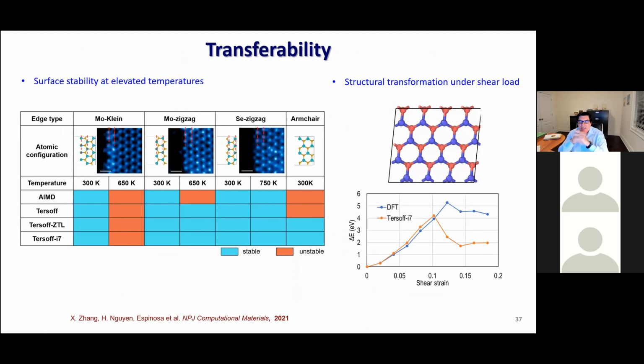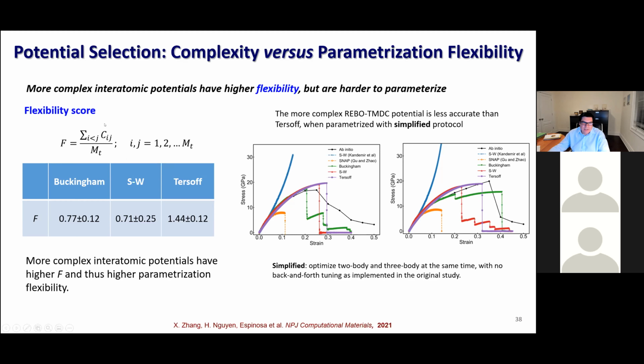And one thing that can be in the back of your mind is, how do I select the force field? What force field do I use? Clearly, you can start with the most complex ones, reactive force field, but is it needed for your problem? By summing all the correlation coefficients and normalizing with the number of properties, we found that we can define a flexibility variable, where larger means more positively correlated properties. And thus, for instance, it's not surprising that Tersoff in this comparison is the best potential that you can obtain. But there are many caveats, as I showed you.